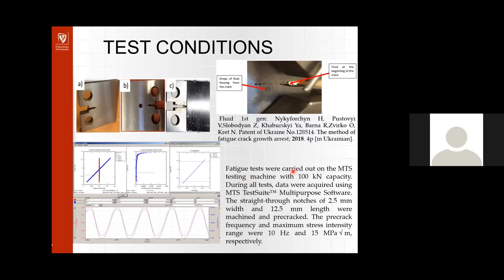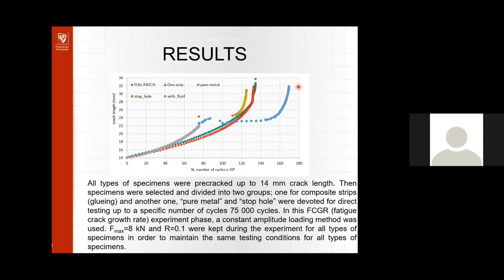In the case of one group of specimens, we used a fluid that was injected by hand — it was not automated, so perhaps not perfectly controlled, but it gave us promising results for the next stage of the experiment. The maximum loading force was 8 kN with a constant stress ratio of 0.1. We started with specimens without any extra procedure from 14 mm up to 22 mm crack length, which took approximately 75,000 cycles. Then we started with fluid injection from 75,000 cycles up to 140,000 cycles.